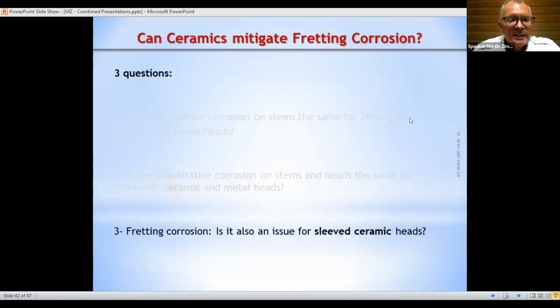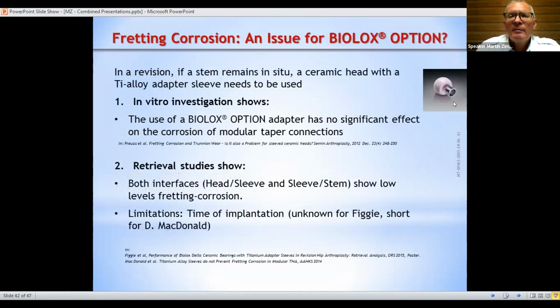Let me go now to the last part of the analysis. What about the fretting corrosion in the case of the Biolox option system with the sleeve? For those who don't know exactly what it is, there's a small picture here. It is a ceramic ball head with a bit bigger taper and there's a sleeve which is typically used in case of revision. When you want to keep the stem in situ and the taper is damaged, then you put the sleeve to avoid using a primary ceramic ball head directly on a damaged taper.